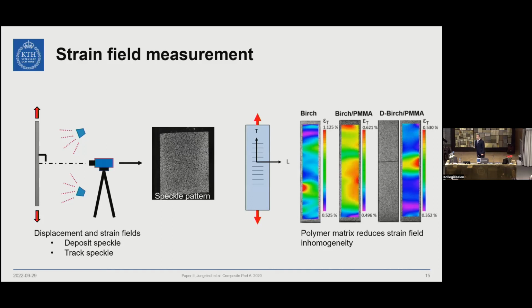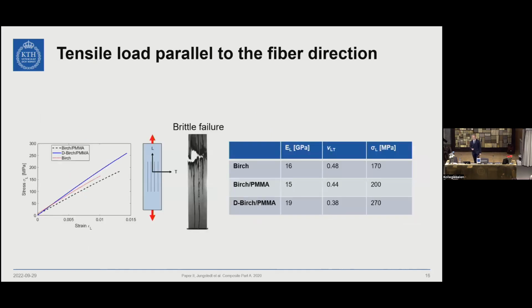And by doing that, we could see from the transverse direction that if we include a polymer matrix, we're actually reducing the strain inhomogeneity in the field. And we are localizing the strains much more, as you can see from this one. So you can see the localized point where it actually fractured in the end. In the longitudinal direction, we have quite a linear behavior up till failure, and then there's a brittle failure. So when you look at the videos and the images, there is no direct evidence for when it breaks. So there's a brittle failure of this material.